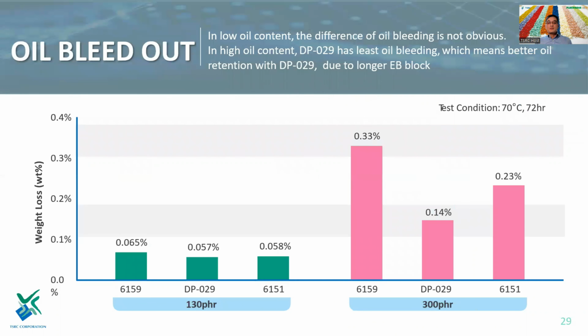On this page, we can see the evaluation of oil bleeding in low oil content and high oil content. In low oil content, the difference in oil bleeding is not obvious. In high oil content, DP029 has less oil bleeding, which means better oil retention with DP029 due to the longer EB block.